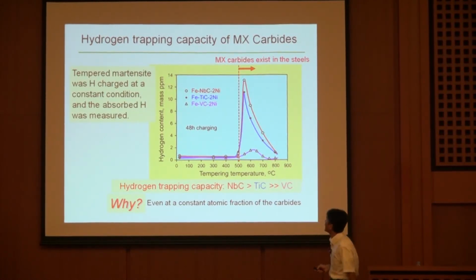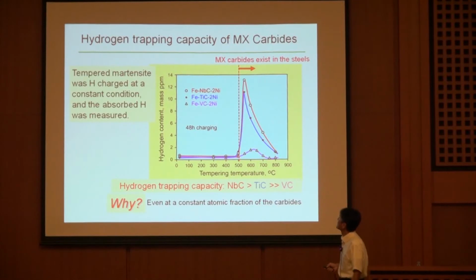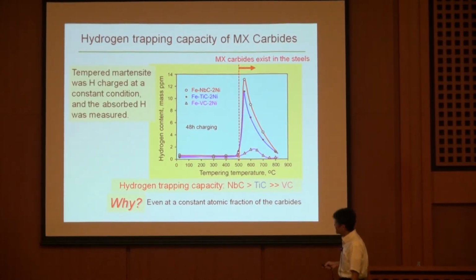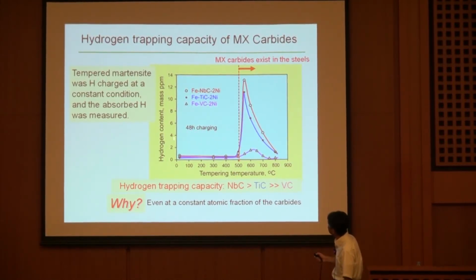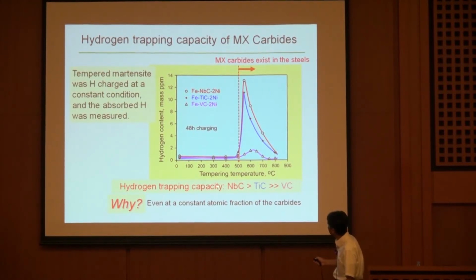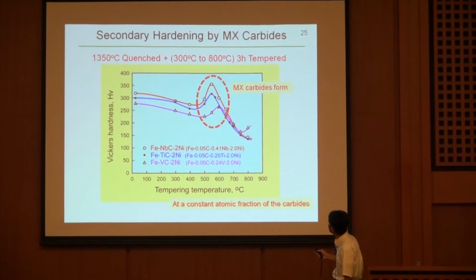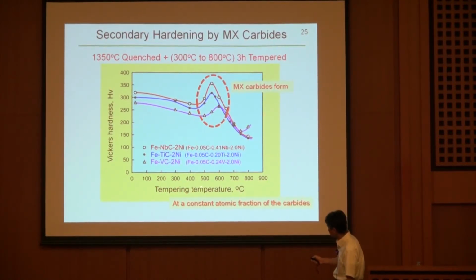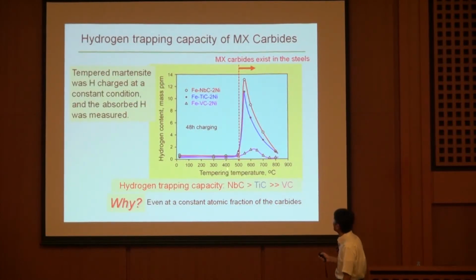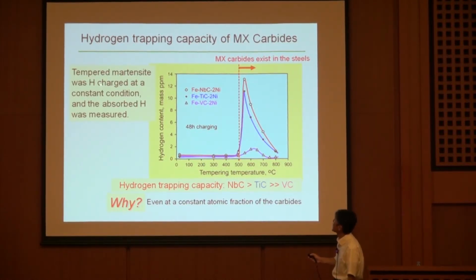Then I checked the hydrogen trapping capability. So this is a little bit complicated. Let me explain. Okay, so this is the hydrogen content, and this is the tempering temperature of the heat treatment condition. Let's go back to the figure. What we've done is tempered martensite with hydrogen charged at a constant condition after the tempering temperature, and the absorbed hydrogen was measured. And this is the result.